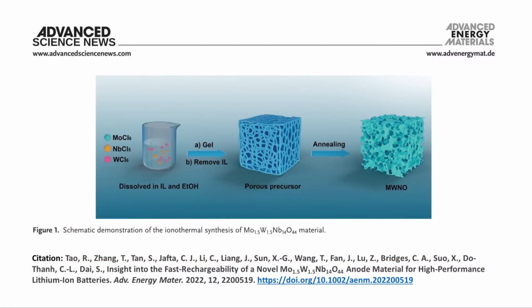So basically, we use ionic liquids as the reaction solvent and the template to dissolve our precursors, which are metal chlorides: niobium chloride, tungsten chloride, and molybdenum chloride. Those three chlorides can be readily dissolved in the liquids. Then we do air calcination, heating the gelled precursor to a certain temperature to form the crystallinity and the metal oxide we want. Yes, that's our process.